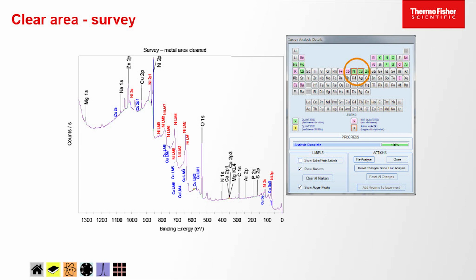These aren't photoelectron peaks. These are, as James was showing you in the cartoon of the atom, after a photoelectron's been emitted, we've left a hole in the electron orbital where it was, and that's got to be filled some way. And one of the ways it can be filled is by what's known as an Auger cascade. So another electron from a higher energy orbital drops down into there. That releases some energy, which causes a third electron to be kicked out. It's a 3-electron process, which means there's quite a bit of uncertainty in it. And so these are the Auger features for nickel here, and you can see they're quite broad because we've got the uncertainty in the energy of 3 electrons in there. So they can be quite diagnostic, and in a moment I'll explain for the zinc how we can actually use those.